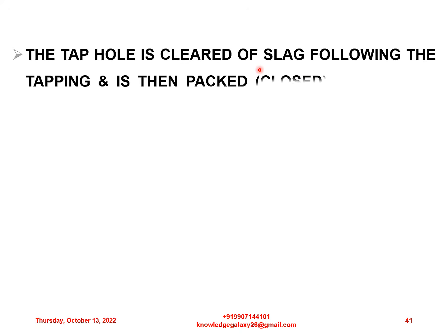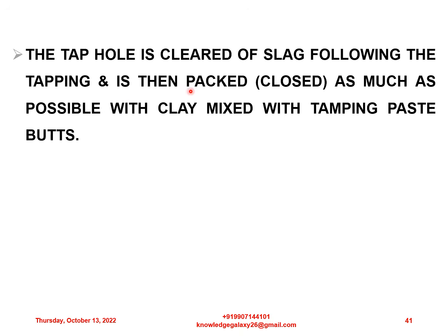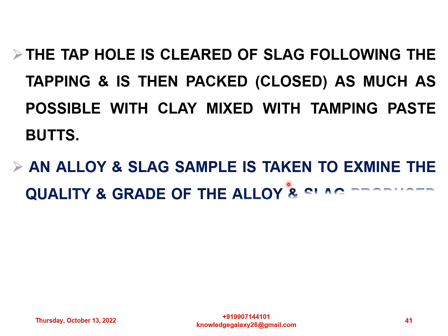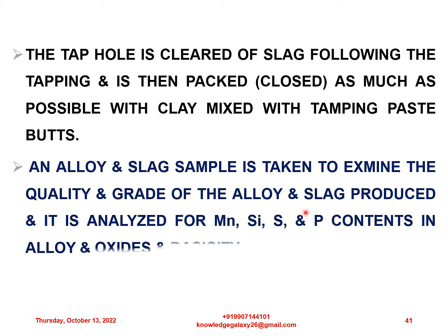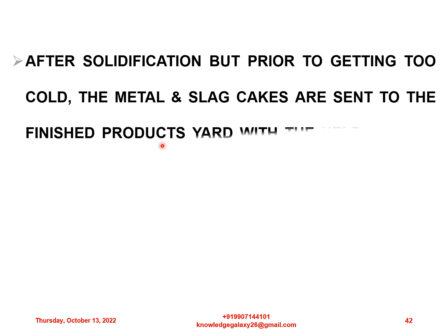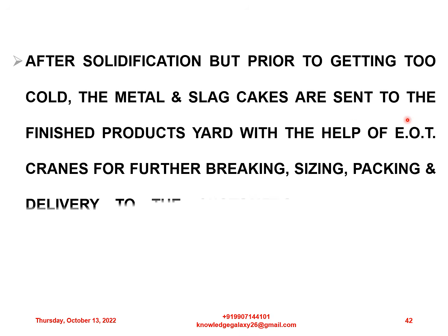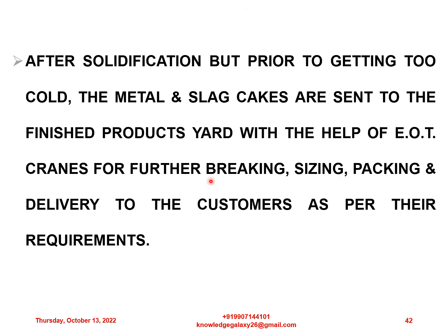The tap hole is cleared of slag following the tapping, and is then packed, that is closed, as much as possible with clay mixed with tamping paste butts. An alloy and slag sample is taken to examine the quality and grade of the alloy and slag produced, and it is analyzed for manganese, silicon, sulfur and phosphorus contents in the alloy, and oxides and basicity in the slag. After solidification, but prior to getting too cold, the metal and slag cakes are sent to the finished product yard with the help of EOT cranes for further breaking, sizing, packing and delivery to the customers as per their requirements.